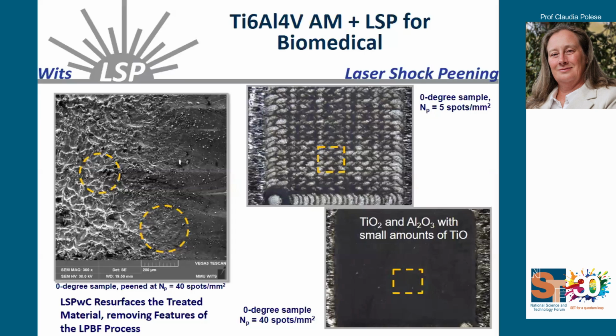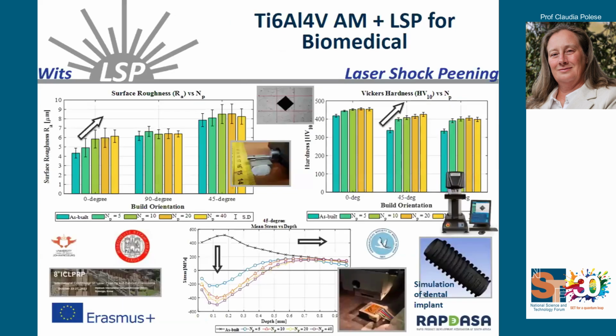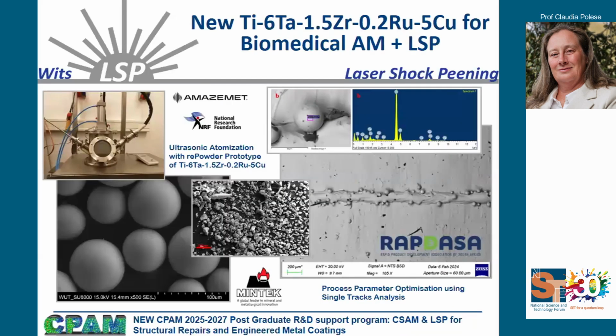And what we saw is that laser shock peening, even without any protective layer, is capable of removing some of the features that are coming from the laser additive manufacturing. It also created some interesting surfaces that are very beneficial from the biomedical point of view. So again, we have a post-processing technology that, combined with another advanced field, is showing very promising results. We're also developing new alloys, because why do we want to stop? Obviously, we want to do additive manufacturing, but we also try to develop new alloys for additive manufacturing, and then potentially post-process also with laser shock peening. So we're starting to be creative in that direction.